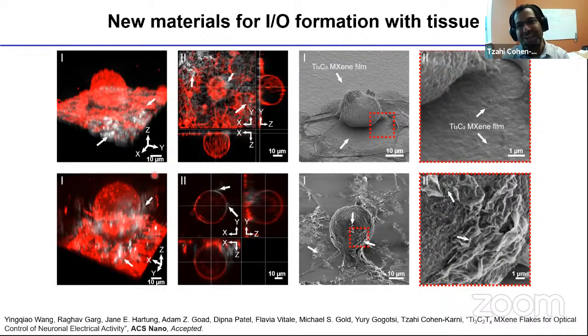which is around 800 nanometer. And this is exactly a textbook wavelength, the first transparency window for the body, where you have lower absorption of hemoglobin and water, basically. So we showed that we can generate films of MXene, and you can see over here the wrinkles in the film. The film is 90 nanometers in thickness, and it's a large-scale film. So it's a few centimeters.